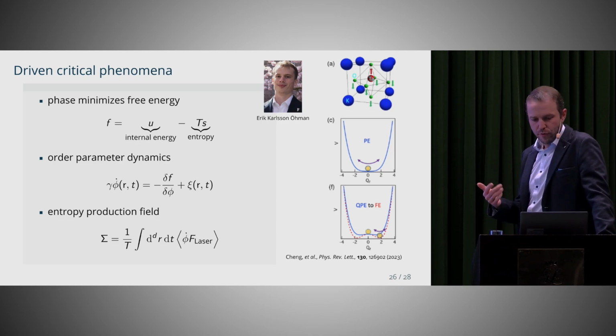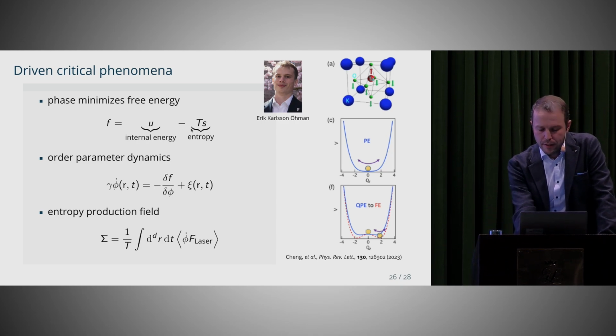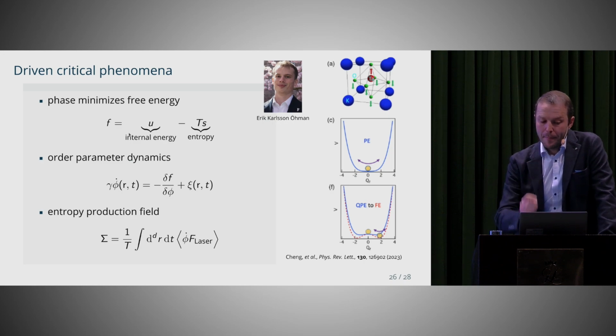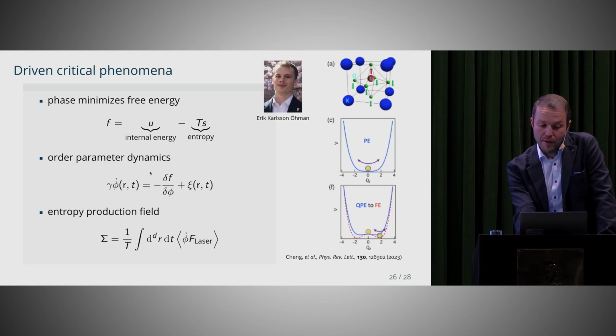And it turns out that for these kinds of systems, if we have a free energy in terms of a so-called order parameter, in terms of a magnetization, in terms of a polarization or whatever, one can write down a dynamics for this order parameter out of this free energy field. And out of that, we again derived a very similar form for the entropy production. So there seems to be a unifying pattern which goes over very different types of phenomena. This is something that the master student, Erik Karlsson Öhman, is working on right now. And he develops quite intense numerical tools to study these field equations.